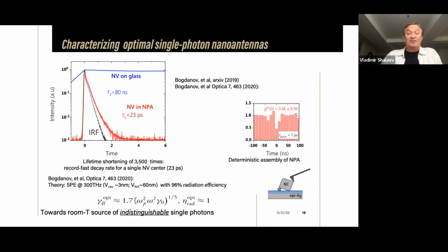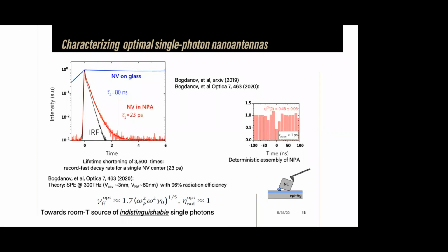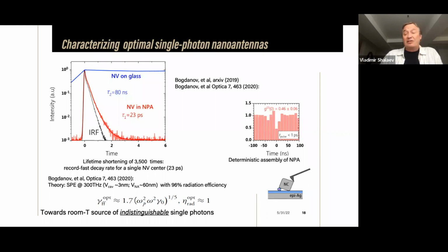Lifetime shortening was 3,500, so the lifetime was actually record short, 23 picoseconds. It was actually shorter than the jitter time, so we couldn't even measure this G2 function with conventional CW lasers. We had to use femtosecond lasers, but we proved that indeed G2 goes below 0.5, so it is a single photon source. And most importantly, if you do calculations, the theory, which was done in collaboration with Jacob Khurgin, it turns out that under ideal conditions, the rate with which photons would be emitted, the ideal conditions here imply that the size of the gap is 3 nanometers, the size of this cube is 60 nanometers, then the efficiency could reach 96%. It's because the photons are not lost, neither to decoherence nor to any decay process. They are emitted so efficiently out. And the rate with which single photons could be emitted could ideally reach 300 terahertz.